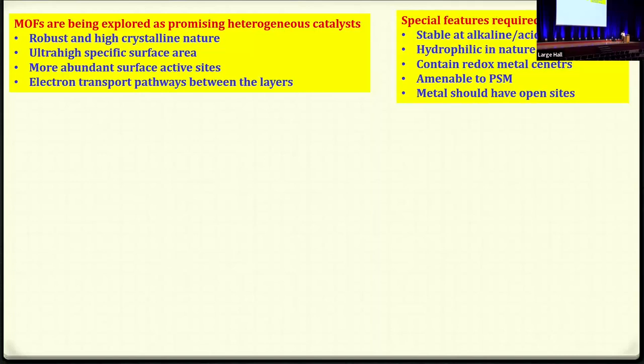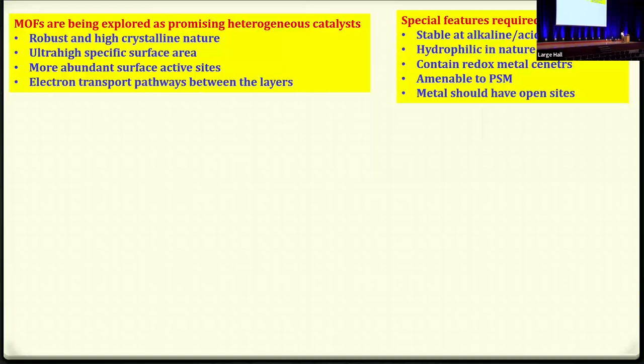The MOFs have to be stable at alkaline and acidic conditions. At the same time, you should have MOFs which are hydrophilic in nature — the cavities or channels have to be hydrophilic. You should have redox metal centers in those MOFs, and they should be amenable for PSM (post-synthetic modification). The metal should have open sites — meaning the metal is not fully coordinated but has solvent molecules coordinated to it that can be replaced with water molecules, which facilitates water-splitting reactions.